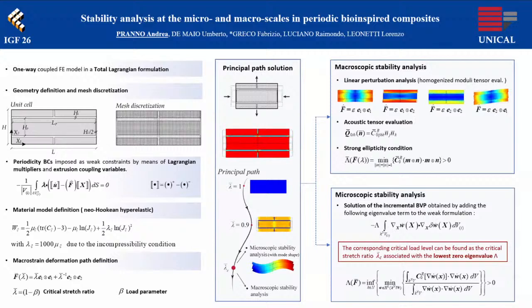Did you see my screen? Yes. Okay. Thank you. In this work, the interchange between the macro and the micro instabilities in nacre-like composite materials has been investigated by examining different combinations of platelet volume fraction and aspect ratio, and shear modulus contrast between the stiff platelets and the soft matrix. The excellent properties of these bio-inspired nacre-like materials are based on the unique arrangement of stiff mineral platelets linked together by a soft organic interface in a brick and mortar scheme.